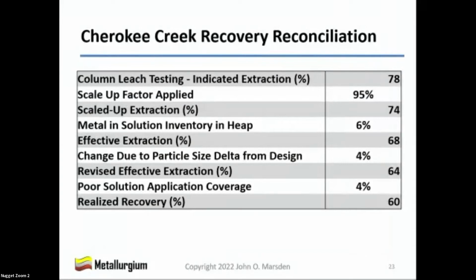Next slide. So finally, Diane did this reconciliation, and she took the original extraction indication of 78%. She applied the scale-up factor. She accounted for the metal in solution inventory in the heap and built that into a good Excel production model. She took into account the particle size differential of 4%, and then the poor solution coverage and lack of side slope leaching was another 4%. So that related back to their recovery of 60% that they were actually getting at the end of year 2. We go to the next slide.